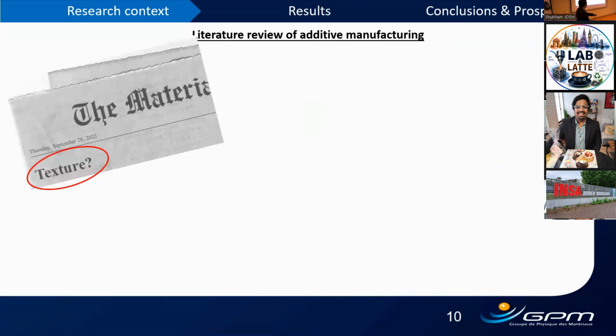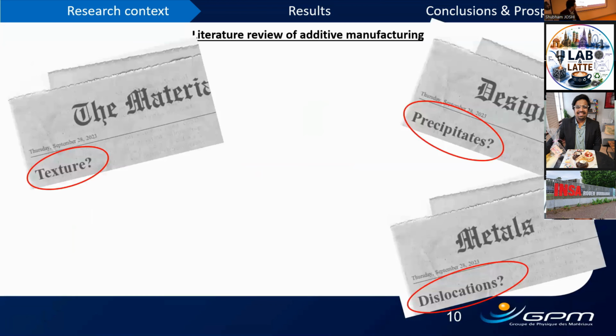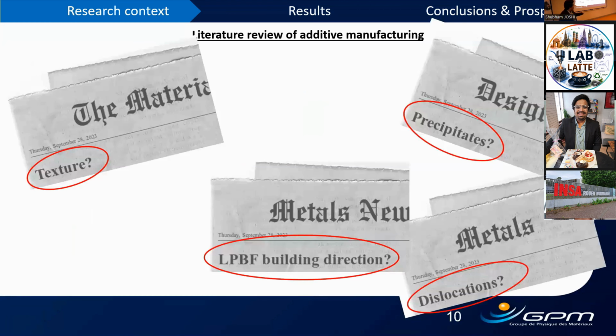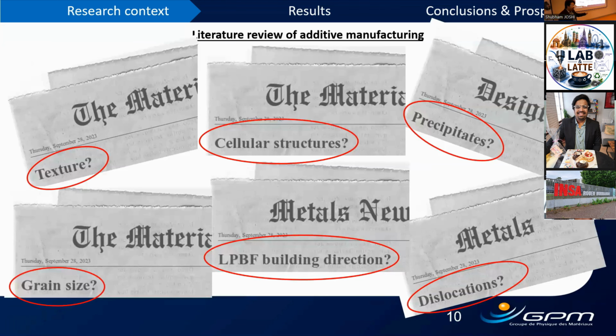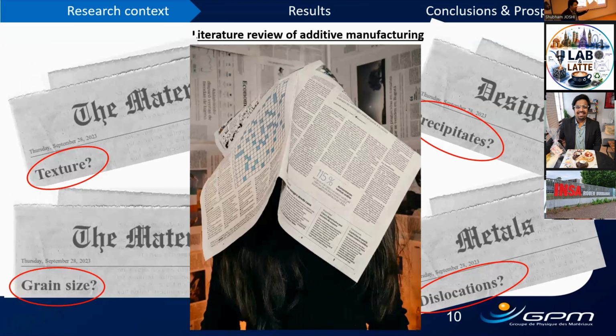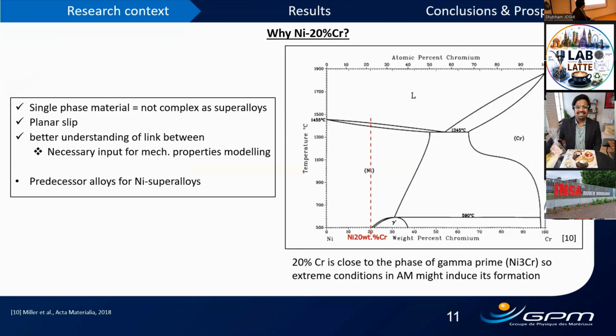And we have so many more microstructural parameters that we can talk about. Just to summarize, can we say that it's an effect of texture, dislocations, precipitates, LPBF building direction, cellular structures, or grain size? Well, it is just the tip of the iceberg, and we have many more problems to come. So to try to avoid this complexity and these difficulties, we decided to employ a simple nickel 20 chromium binary alloy, which has a simplified microstructure.